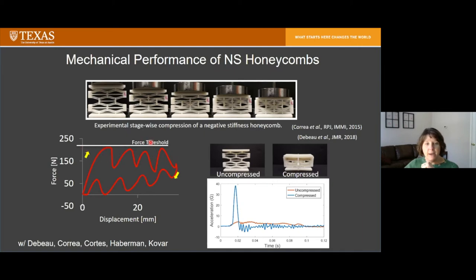One of the cool things about this, though, is as it absorbs energy, it does that at a reasonably constant force threshold, and we can engineer that force threshold so that we can mitigate impacts at a prescribed acceleration or force threshold level. Here you can see one honeycomb, and you can see its architecture. And so we've dropped a heavy mass on top of this honeycomb when it's uncompressed and when it's compressed.